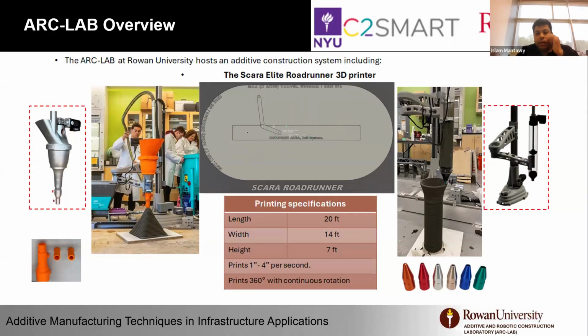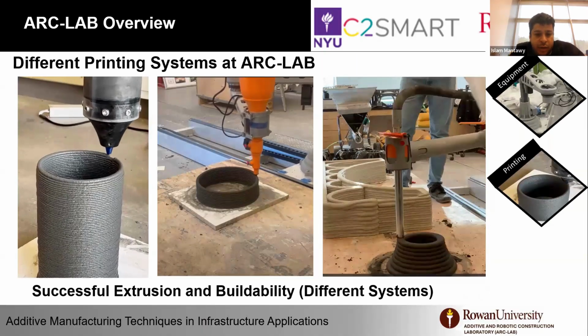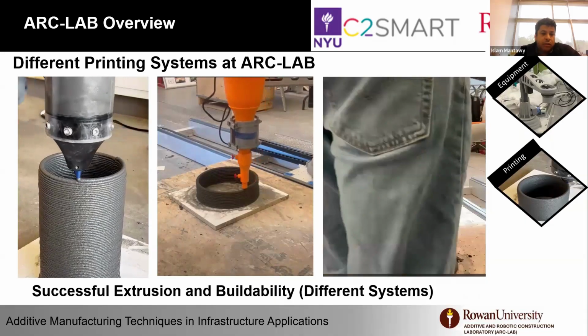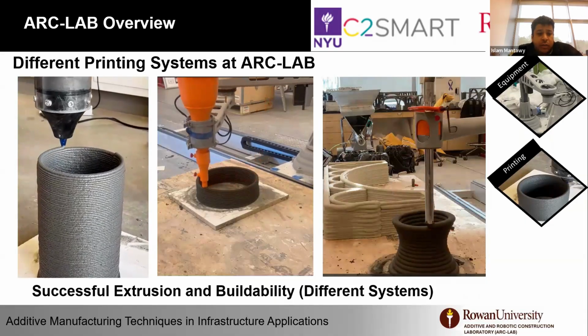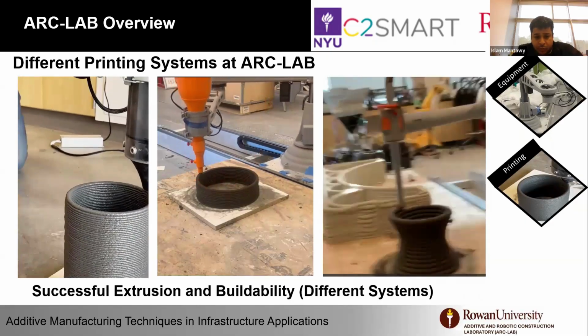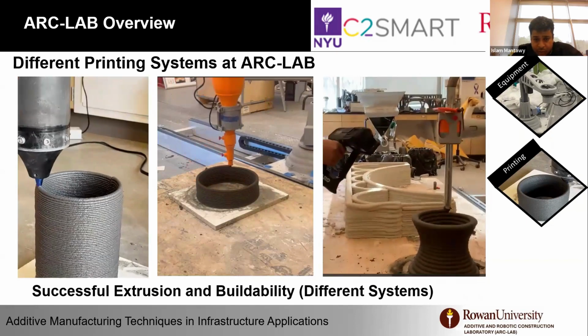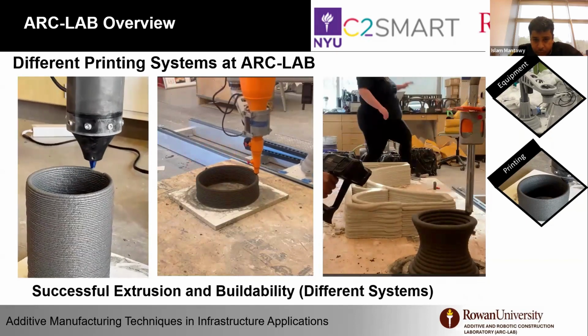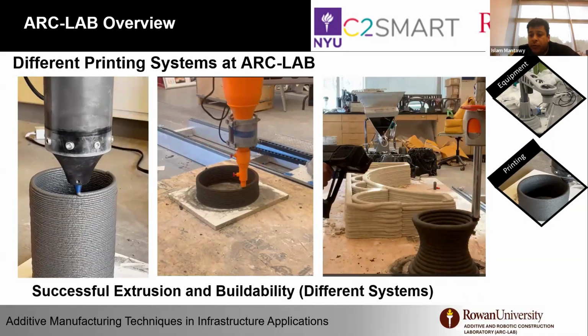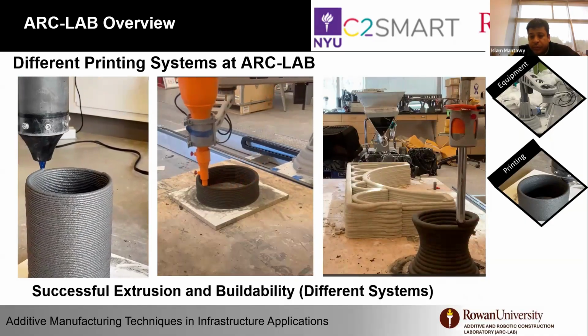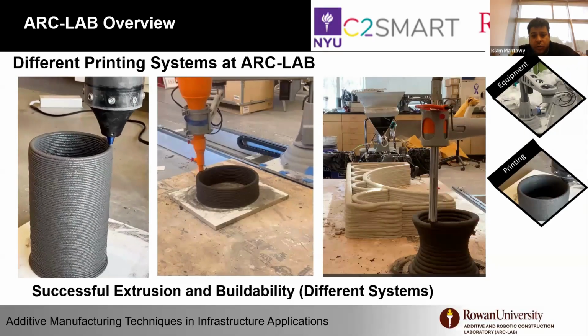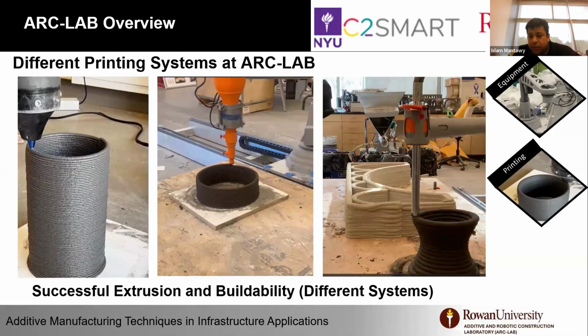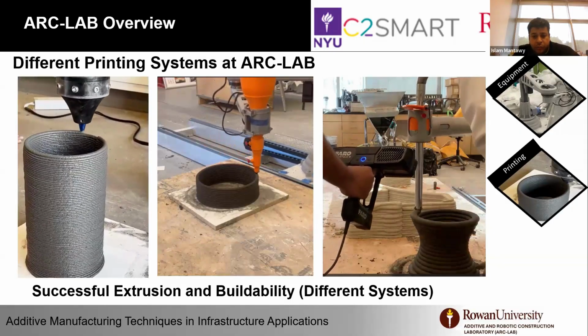This is a printer that we have in place, and I just explained the capability of it, and I will show you later on the more capability that we're going to be adding soon. The system we have can print really small scale, up to like an 8 millimeter nozzle on the left side using a syringe tube, and can scale up to 1.5 inch layer thickness. As you can see here, in the middle one we're using an auger system, and on the right side we're using direct pumping from the pump to the nozzle. The same material is being printed from a tube, to an auger, to the printing system, and you can see the quality of the print here.